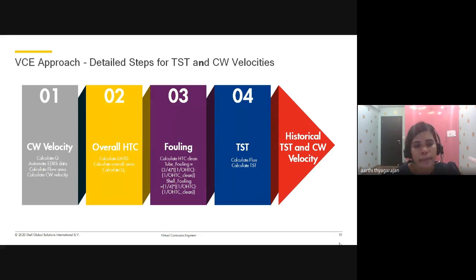What we show here is nothing but the basic heat transfer fundamentals that we have used, and basically we calculate the velocities, the heat transfer coefficient, fouling factor, and we calculate the tube skin temperature. Based on the calculation of tube skin temperature and the knowledge of the equipment, we know the limits for each equipment, we can calculate the exceedance on a live basis, and knowing the historical exceedance and the live exceedance, we can calculate the cumulative exceedance, and then you correlate with respect to the corrosion rate based on the inspected heat exchangers, and based on the correlation further you calculate the corrosion rates for the unknown heat exchangers. So that's the summary of how we applied this augmented intelligence for the heat exchangers in VCE.